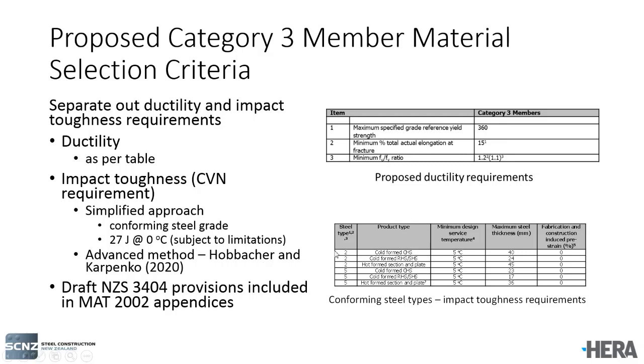We have for the Type 2 and the Type 5 steels, which is what 3404 Part 1 2009 had, some limitations in terms of the minimum design service temperature of 5 degrees. We also have some maximum steel thickness requirements, and there's also a requirement that the steel hasn't been subject to any fabrication or construction induced pre-strains.